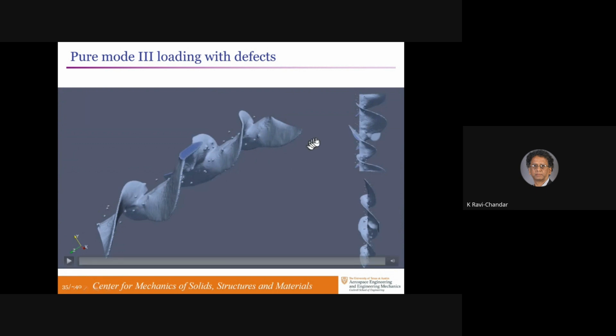but you could see the sense that the cracks are slanted at 45 degrees for a pure mode 3, and they do what we expect them to do. They appear autonomously once the defects have been produced in there. Ideally I would have defects everywhere in the entire volume, but you can already see that those defects are not going to do anything, because defects that are left behind are unloaded and they don't play a further role in the evolution of the crack.